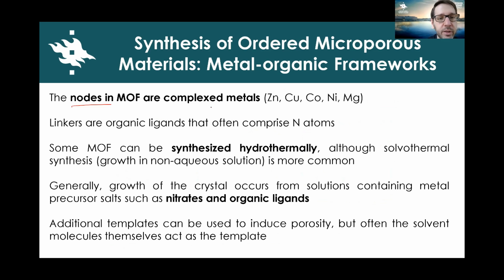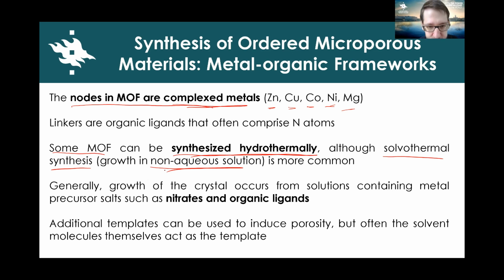So normally the nodes in the metal organic frameworks are composed of complex metals, usually zinc, copper, cobalt, nickel, and magnesium. Linkers are organic ligands, and they can also comprise nitrogen atoms. Some metal organic frameworks can be synthesized hydrothermally by heating the precursors in aqueous solution to induce the reactions that will generate the metal organic framework structure. But in this case, solvothermal synthesis, which is the same procedure using non-aqueous solution, is more common because of the organic linkers that are used.